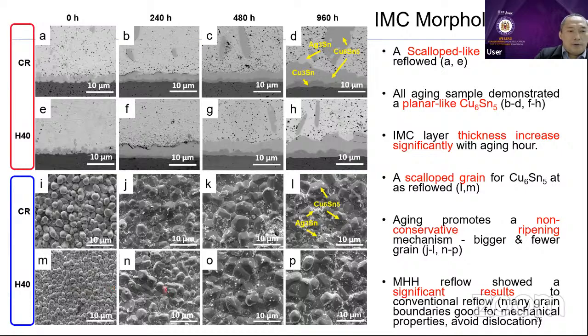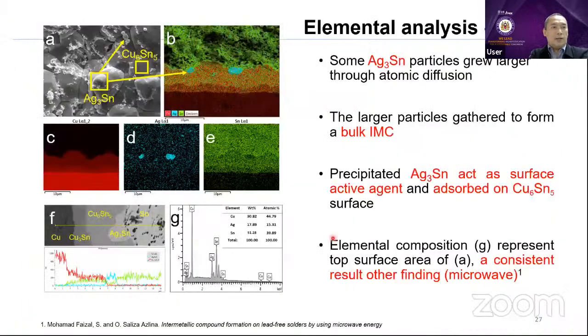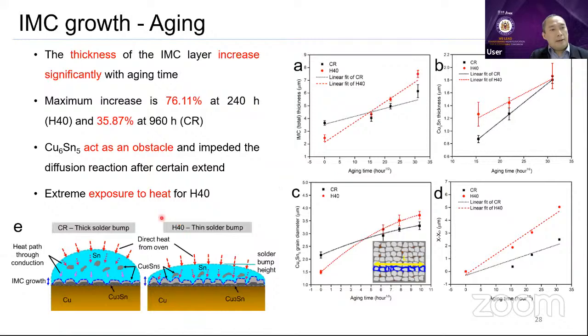Okay, and then when we run for a longer time, we can see the differences in the grain size and the formation of white powder here. The white powder refers to the Ag3Sn. We also had some opportunity to do this color index, and we can see that for the longer time, the Ag3Sn tends to be very big here and so on. Okay, and then this one is the IMC growth.